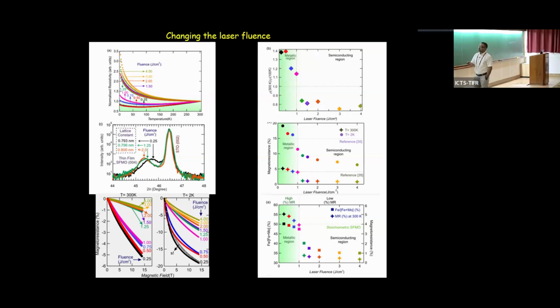So this is the magnetoresistance. And you can see at low temperature, we could get around 20%. And at room temperature, we could get around 6% of the magnetoresistance with changing the laser fluence, which is almost double what people had seen for all reported thin films. So by changing the laser fluence, what are we actually changing?